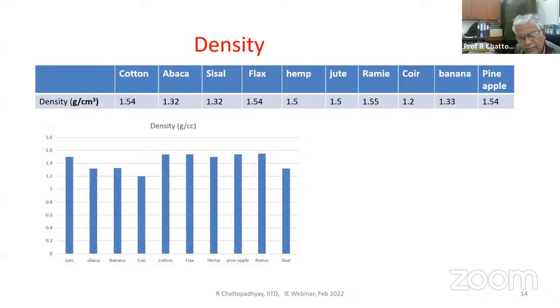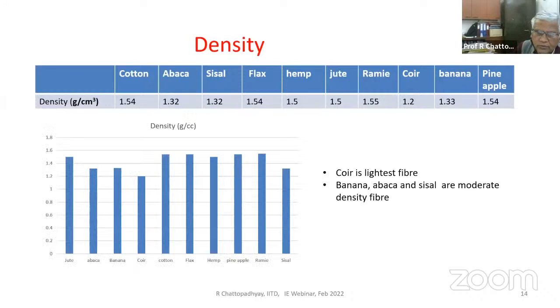The other one is, again, density of these fibers. Most of these fibers have a density close to 1.5 to 1.54, but there are some natural fibers which have a lower density, like coir at 1.2 as reported. Similarly, abaca and sisal are relatively low density fibers, at about 1.3. The rest are close to 1.5. So coir is a very light fiber, whereas banana, abaca, and sisal are moderate density fibers. So there is a density variation in plant fibers also.